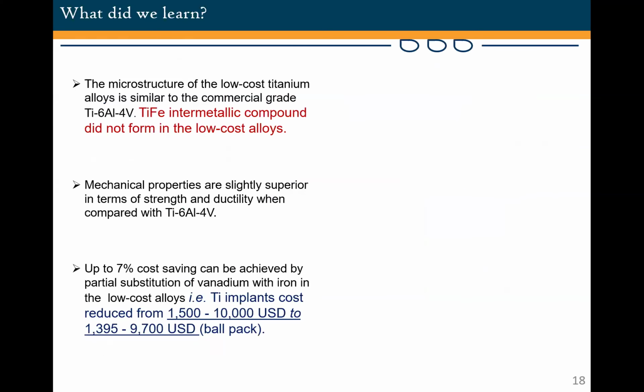Now, what have we learned so far? We were able to suppress the formation of TiFe by the idea of having that partial substitution of vanadium with iron rather than the full replacement that has been done previously. Again, we improved the strength slightly, and of course, we even have improved ductility.